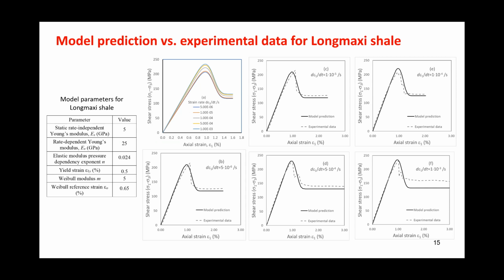Okay, so this is a comparison of model prediction versus experimental data for the Longmaxi shale that I showed you a while ago. These are for all the strain rates from 5 times 10 to the minus 6 to 1 times 10 to the minus 3. These are the individual results of the shear stress versus axial strain, from an axial strain rate of 1 times 10 to the minus 5 all the way to 1 times 10 to the minus 3. You see the fits are remarkable, very good. Sometimes though the residual shear stress is slightly lower than the experimental data, but overall, I think this is satisfactory. Now let's move on.